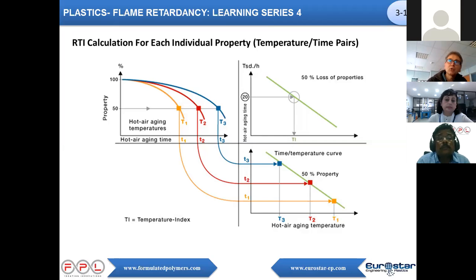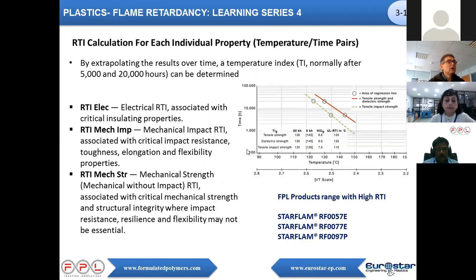Some customers are also requesting the thermal index at 5,000 or 20,000 hours, but that can be extrapolated from this curve. So it's a very important data. It's also maybe a bit questionable because there is no absolute property. And when you do a test, you always do it in comparison with a standard, with a competitive material.